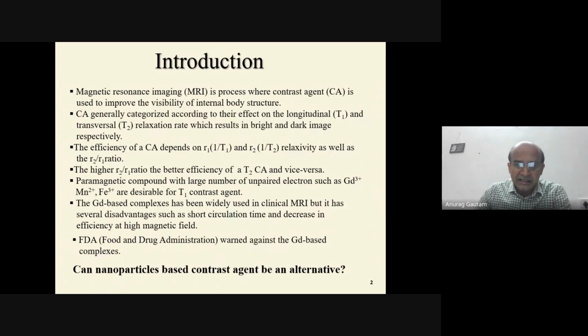There are some ions that have been used in the past, paramagnetic compounds with a large number of unpaired electrons, such as gadolinium, which has 7 unpaired electrons, or Mn2+ or Fe3+. They all give T1 contrast. At present, at clinical level, as I said in the beginning, we are using Gd-DTPA and some other complexes. The machine at clinical level was earlier, I think a couple of years back, 1.5 Tesla, but now MRI machines also operate at 3 Tesla. In animal models, they have already gone to 7 Tesla. The higher the magnetic field, the better the relaxation rate and the better the contrast. But they have gone to 7 Tesla only for animal MRI.